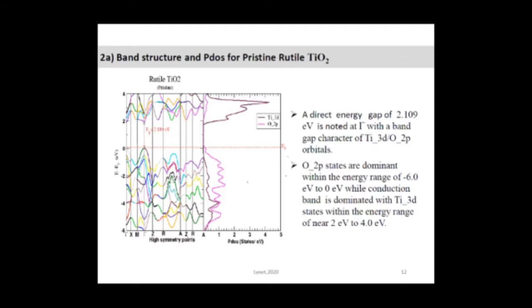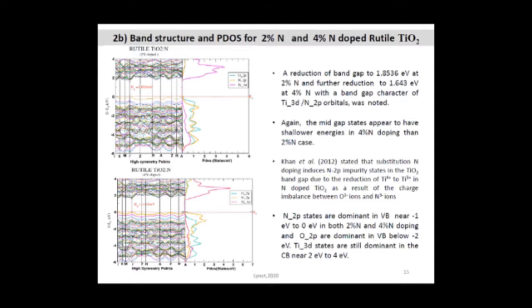And you can also see the energy ranges. The same thing that you observed in anatase is still observed here: the band gaps are reducing for the doped materials. What contributes majorly to the reduction of these band gaps is the nitrogen 2p orbitals. This was also observed by some researchers, who attributed it to the reduction of titanium when nitrogen replaced oxygen sites in nitrogen-doped TiO2. That was Khan et al. in 2012.